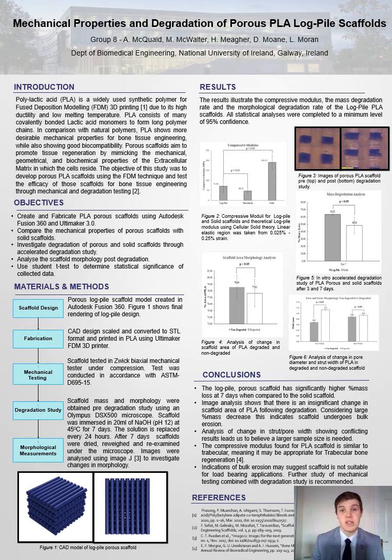Analysis of the change in the strut and pore width showed conflicting results. This may be due to the limited sample size. In order to get more accurate data, a larger sample size may be required. Indications of bulk erosion suggest that the scaffold is not suited to load-bearing applications.